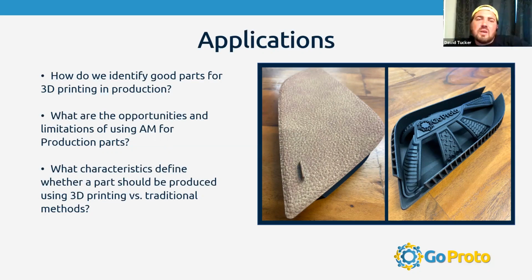That's a huge difference. The main innovation, where you see these technologies going, is from point-based to area-based, and from area-based to continuous. That's the technological change. Multi-jet fusion is an area-based powder process, so it processes on an area level. Therefore it has consistent build times, whereas the time it takes to build something in an SLS process can vary, because it's based on the number of lasers and the speed and accuracy of those lasers to trace, fill and raster. Those differences lead to performance differences in materials, and also economic differences due to speed and productivity. It's all that transition: is the technology point based? Is it area based?